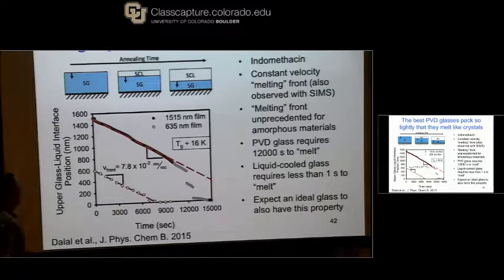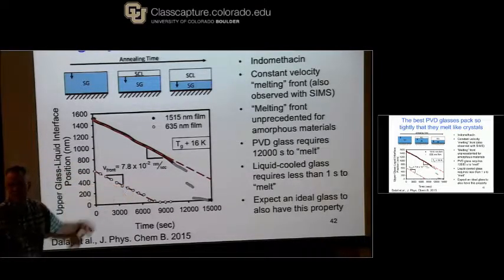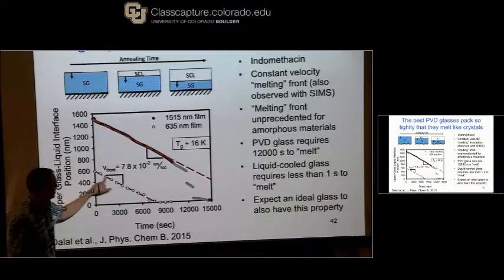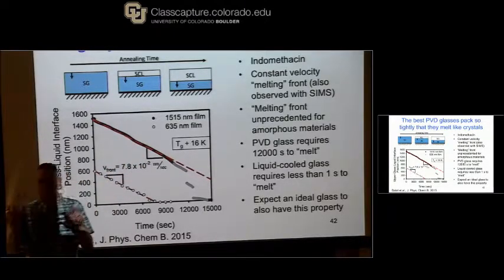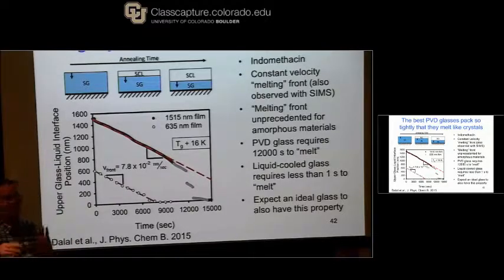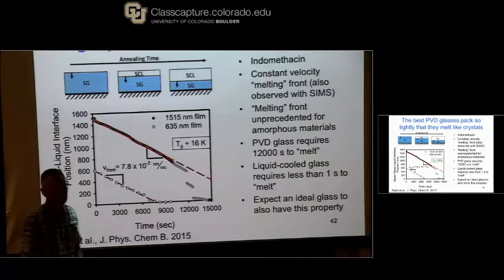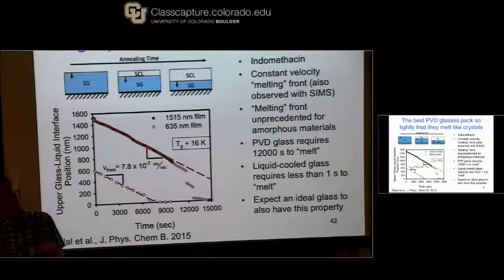Okay? You can repeat the experiment with a thinner sample that's prepared the same way, and you get the same slope. Right? So if this were a crystal, we'd say this is the melting velocity of the crystal, and it should be independent of the size of the crystal. So this really is behavior that's analogous to crystals. I had never really thought about this carefully before, but of course the whole reason why crystals do this has nothing to do with periodicity. It has to do with the fact that the barriers for rearrangement are much higher in the middle of the crystal than at the surface of the crystal.